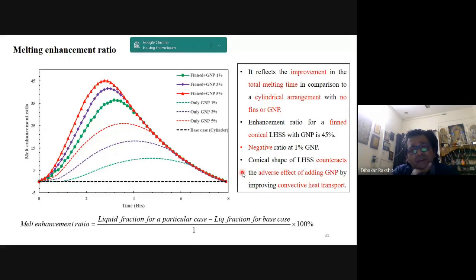There is one more thing, as I was telling about the turnaround efficiency: the melting enhancement ratio of that particular thermal battery, which is quite important to understand. So you can see the melting enhancement ratio when we have different combinations of fin, GNP, and only GNP in different percentages by volume, compared with the base cylinder, which has the cylindrical shape. You can see there is an improvement in the total melting, and that helps us understand that it is always better to have a conical type of thermal battery in comparison to a cylindrical arrangement. The enhancement ratio of the fin system for the conical system with GNP is also reported, which is around 45%.